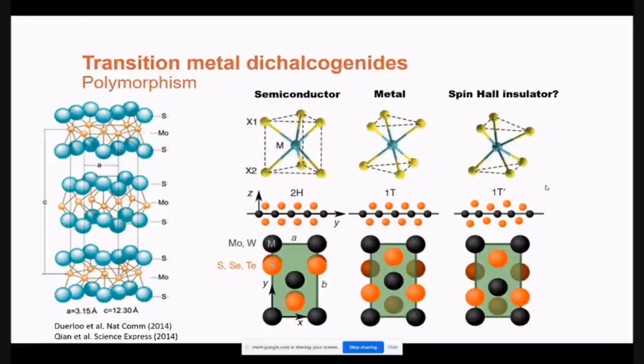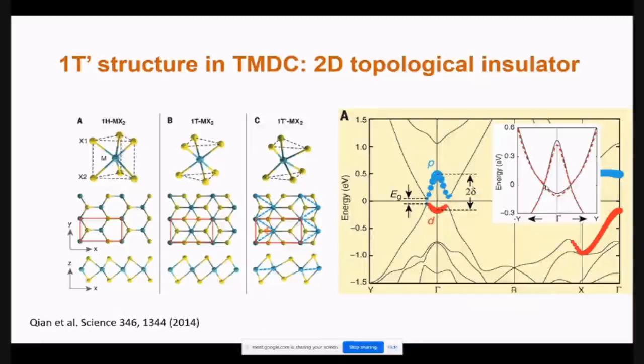But here, of course, strong spin orbit interaction is the protection mechanism, and calculations are now available, and there are experiments available as well, primarily through scanning probe, in which you can see that in the case of octahedral molybdenum disulfide, the band inversion is happening here. Okay? I'm not going to go into detail at this stage.